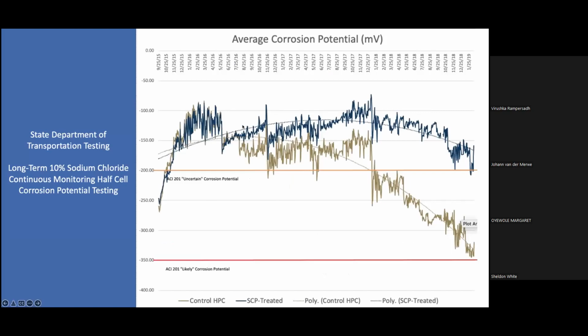Now, real quick, this was a State Department of Transportation's corrosion lab investigation, in a 10% sodium chloride solution with continuous half cell monitoring. ACI gives you an uncertain corrosion potential line here at negative 200 millivolts. You can see that the control specimen somewhere around the 2 year mark starts dipping into the uncertain corrosion potential, and by the 3 year mark, it's really headed toward the likely corrosion potential occurring. So for the treated sample, you can see the difference in corrosion behavior. And this was what's called a high performance concrete or HPC mix.